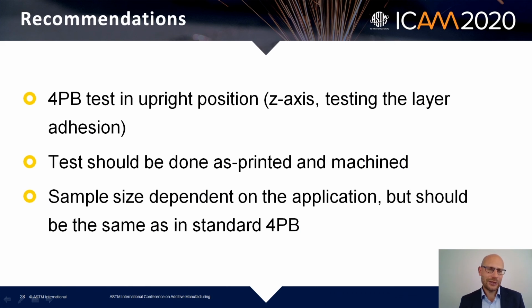But what is now the recommendation for how to really test additive manufactured parts? Our recommendation, this is what we are really trying to educate the market a little bit on, is how it can be tested. First of all, we prefer 4-point bending over 3-point bending, because it gives you a bigger volume which can be tested. And this is definitely a must, I would say, to test all parts in upright position, so that you are testing the layer adhesion. Usually this is the Z-axis.